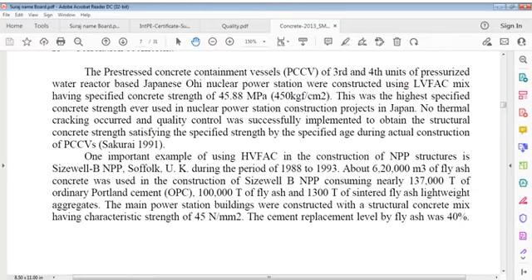Test concrete containment vessel. Pre-stressed concrete containment vessels of third and fourth units of the pressurized water reactor based Japanese Ohi nuclear power station were constructed using LVFAC mix having specified concrete strength 45.88 MPa. This was the highest specified concrete strength ever used in nuclear power station construction projects in Japan. No thermal cracking occurred and quality control was successfully implemented to obtain structural concrete strength satisfying specified strength by specified age during actual construction of PCCVs.